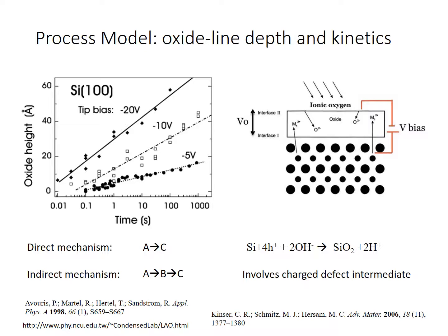To conclude, oxidation SPL in the AFM can be characterized by a straightforward process model, making it one of the most repeatable and well understood scanning probe lithography techniques. It's a direct write process, which means that it doesn't require any subsequent development steps or liftoff, unlike electron beam lithography. And the fabricated structures are imaged in parallel with writing. However, one drawback that scanning probe lithography faces is the low throughput. Similar to electron beam lithography, scanning probe lithography is not a parallel process, which makes it unrealistic for large-scale industry processes. So the next steps in the field of scanning probe lithography are being taken to develop parallel writing processes.